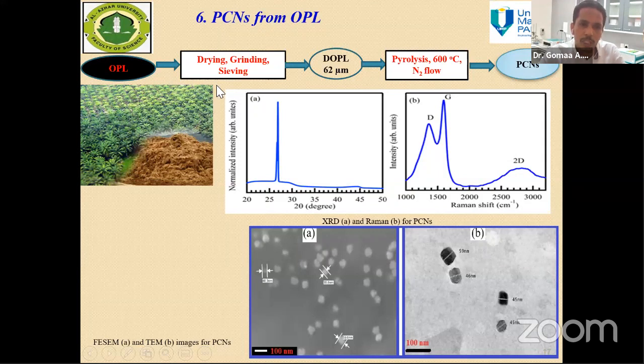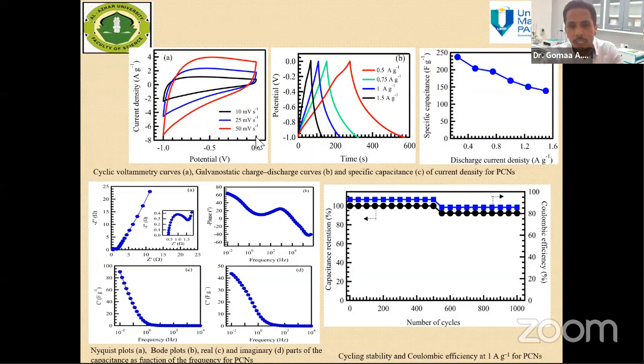So we use these palm oil leaves, grinding, then pyrolysis at around 600 degrees in nitrogen flow. So we obtained porous carbon nanospheres, and this is some characterization showing the carbon structure of the prepared materials, Raman and X-ray diffraction. And under SEM and TEM investigation, showing the spherical particles of carbon nanomaterials. So this material has been tested for electrochemical application, testing for supercapacitor application.